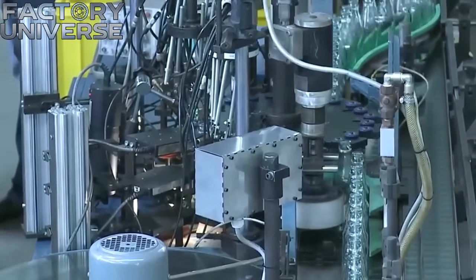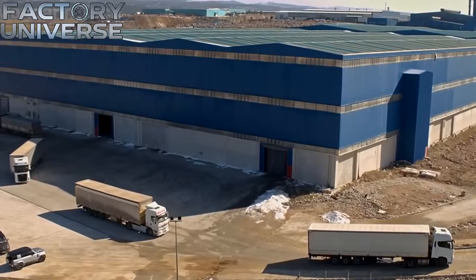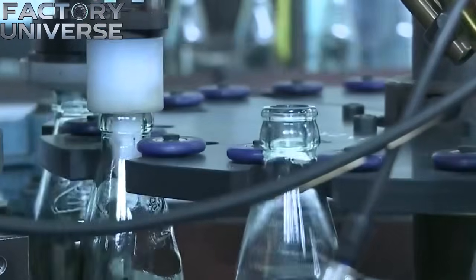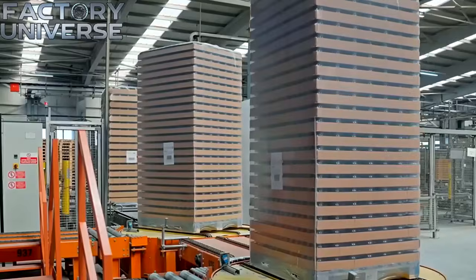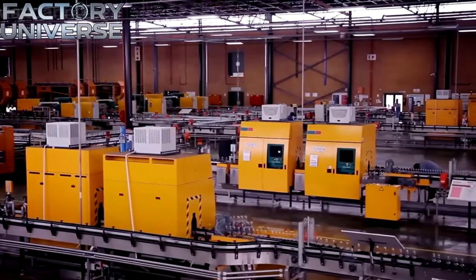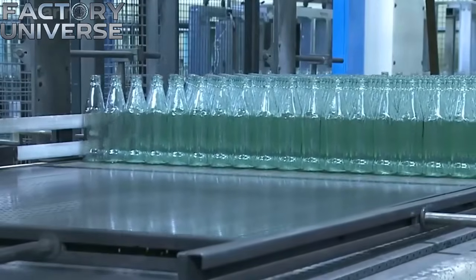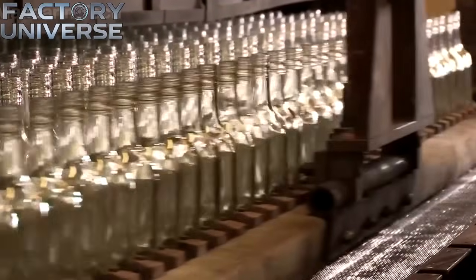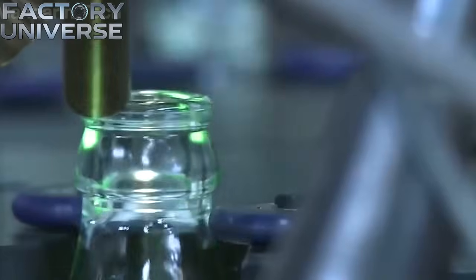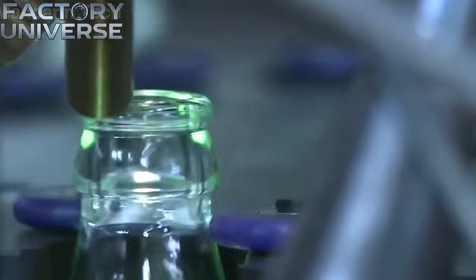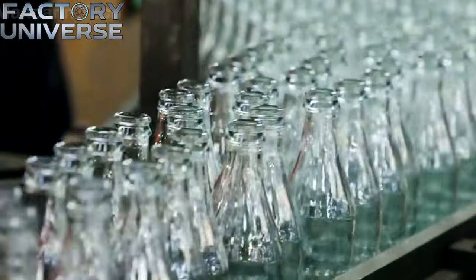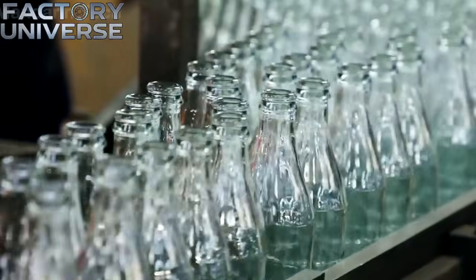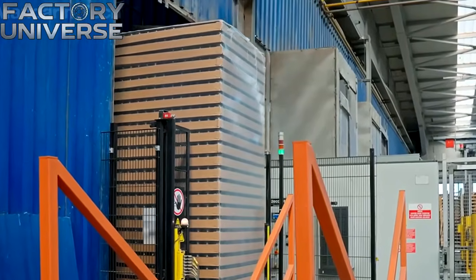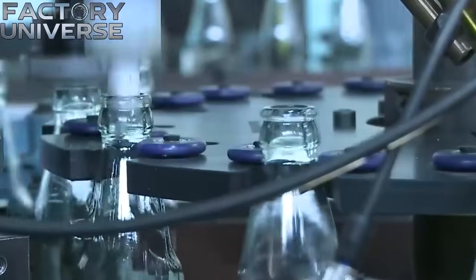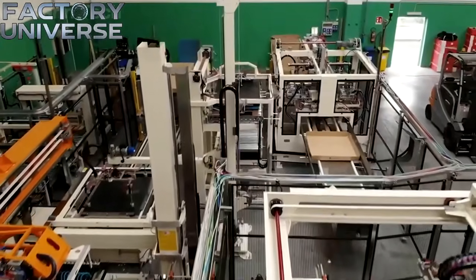Once the cooled glass bottles exit the tunnel, they reach a high-precision inspection station. Here, an array of optical sensors and high-speed cameras examines each unit in real time as the equipment moves with rhythmic mechanical clicks. Every microscopic detail is checked. The moment a defect appears, whether it is a crack, a gas bubble, a surface scratch, or even a tiny structural warp, the automated system flags the item. Pneumatic ejectors immediately pull the flawed bottle off the production line. One can notice how the rejected glass is diverted into a separate chute for remelting. It gets more complex further on.